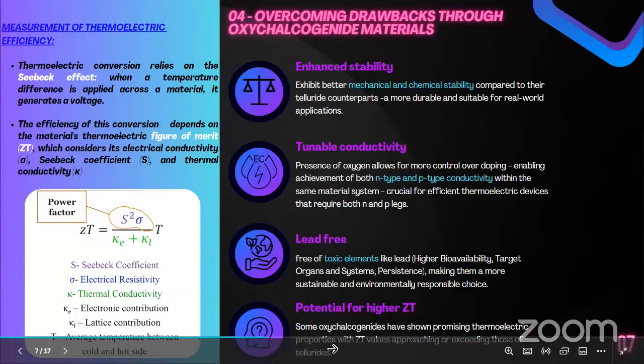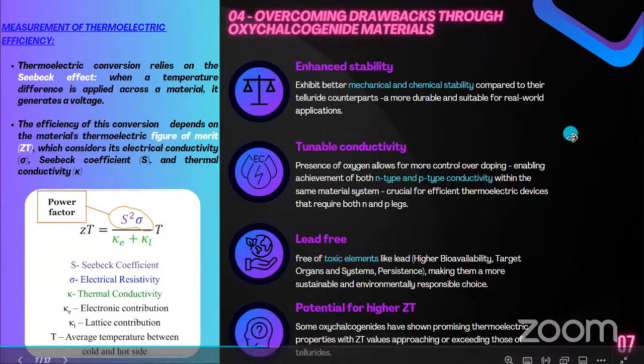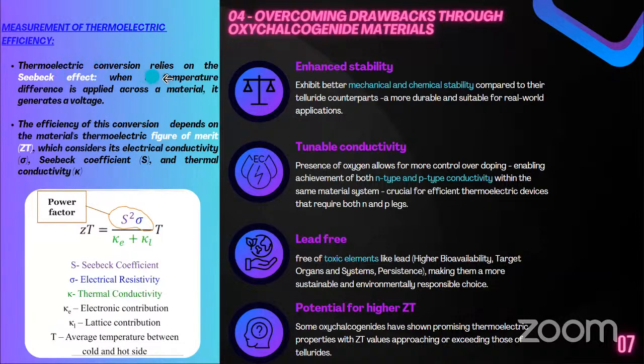Measurement of thermoelectric efficiency and how we are overcoming those drawbacks through oxychalcogenide materials. Measurement of thermoelectric efficiency. The thermoelectric conversion absolutely relies on the Seebeck effect. When a temperature difference is applied across a material, it generates a voltage. So the efficiency of this conversion depends on the material's thermoelectric figure of merit, which considers its electrical conductivity, Seebeck coefficient, and thermal conductivity, where ZT is equal to S squared sigma divided by (Ke plus Kl) times T, where S squared sigma is called the power factor.